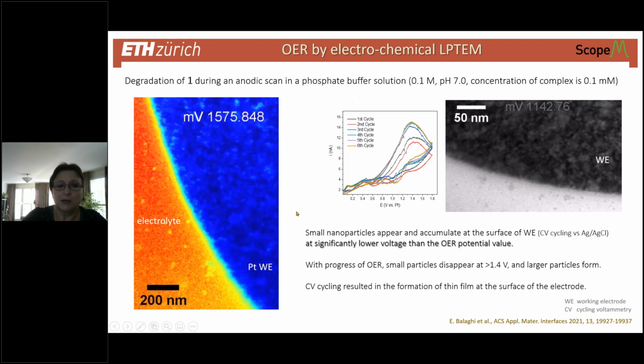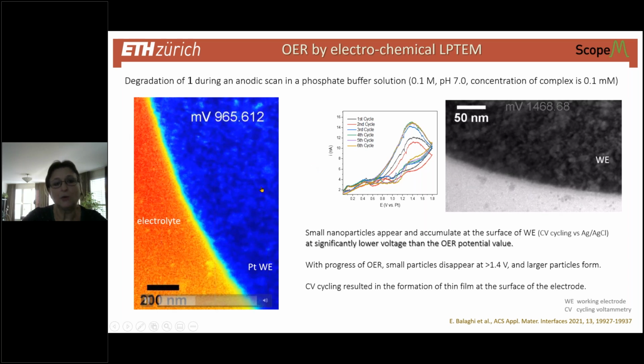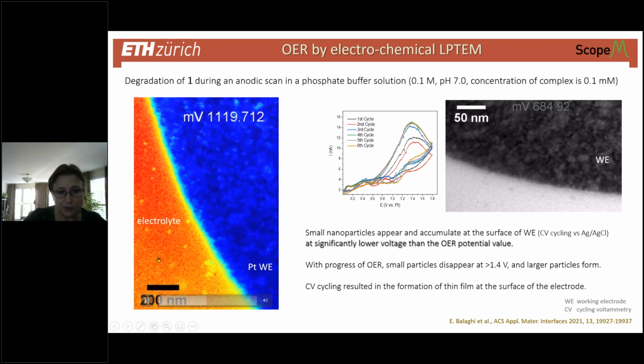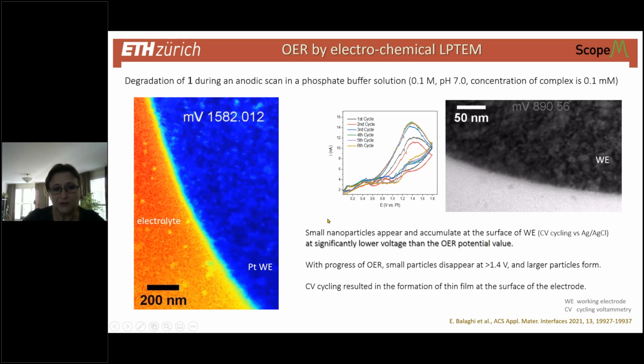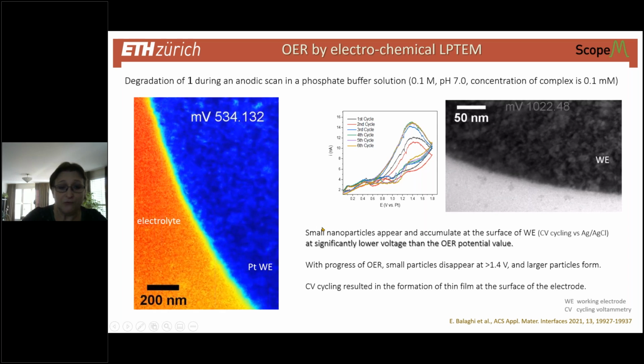When we run the potential up, you see that small nanoparticles appear at the surface of the electrode. You see they're growing. Then, given time, the smallest particles dissolve. Maybe one does not see it from the movies, but you trust me on that. I have more data. And larger particles form. With the progress of the reaction, small particles disappear and large ones form. This is not a part of the movie.